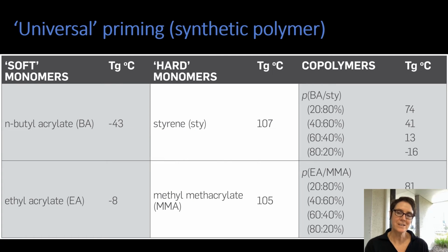Although characterization of the percentage combinations of monomers was beyond the scope of this study, it's useful to note that different monomers are combined to achieve desired acrylic product characteristics, such as softness and hardness. You can see here that combining a higher percentage styrene to butyl acrylate, for example, results in a polymer with a higher Tg, thus a harder polymer. We were surprised to find so many different formulations of copolymers, even within brands, and this indicates that there is a wide variety in the manufacture in the coatings industry.